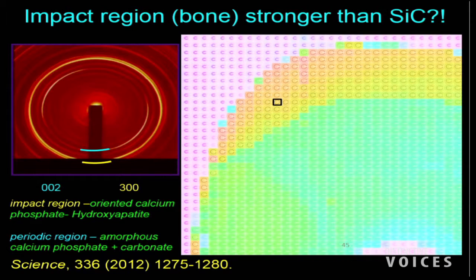And we found that the outer region that you saw in the other micrograph that was white is a highly crystalline and oriented calcium phosphate, specifically the same mineral that's found in your bone. So this is a bone-like mineral that's highly oriented, made at room temperature, and stronger than an engineering ceramic that's famous for being quite strong, silicon carbide. So it's quite impressive. The inside of the club also consists of calcium phosphate and calcium carbonate, other minerals, but it's amorphous. There's no periodic arrangement of atoms within the structure.